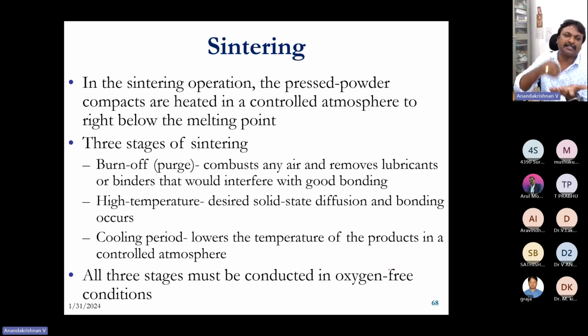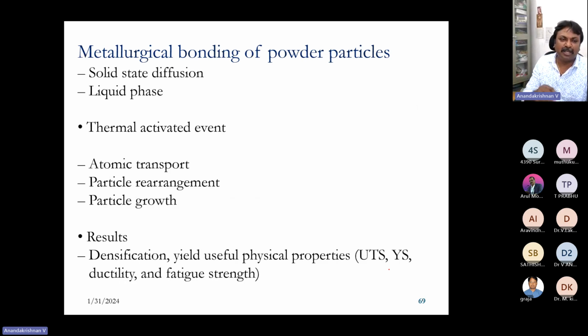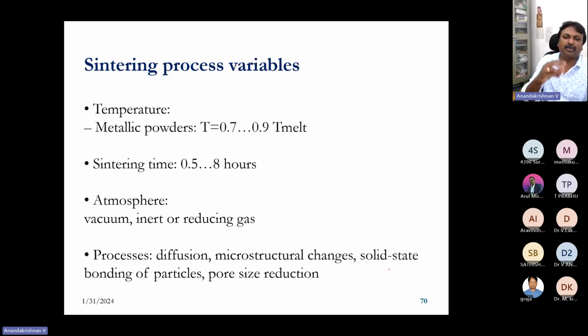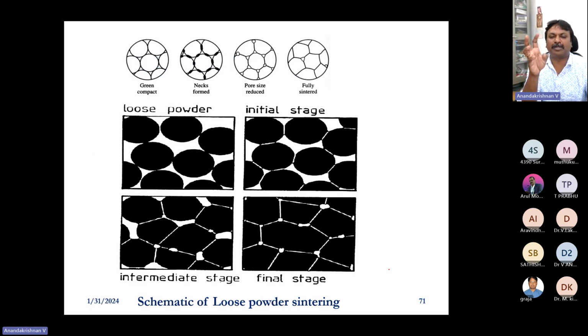For example, a glue-like structure, you can attach particle to particle. So the 3D component is having all the particles together by means of a temporary joint, by means of any adhesive or some material. Then you can put it inside a furnace and heat it. When you heat it to 70 to 90% of the melting temperature of the material, for half an hour to 8 hours depending upon the size, in an inert atmosphere, what happens? The particles get attached together. That's called the sintering process.